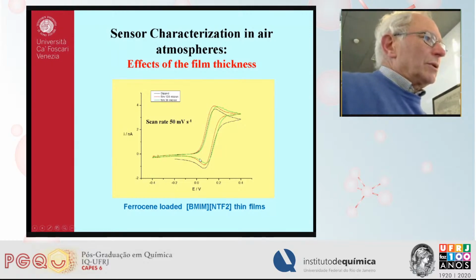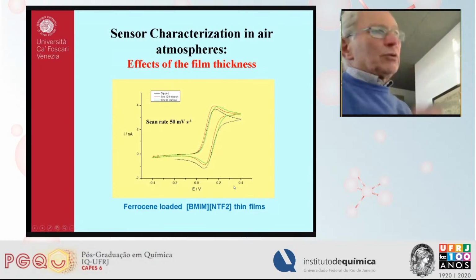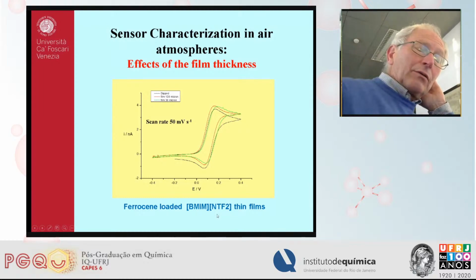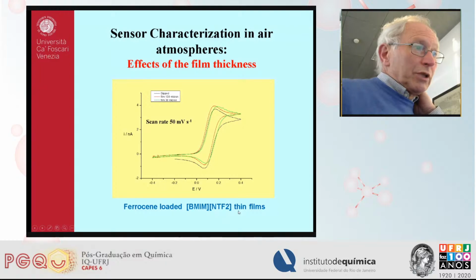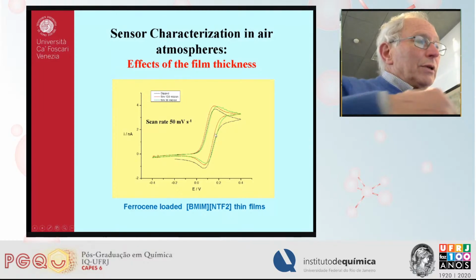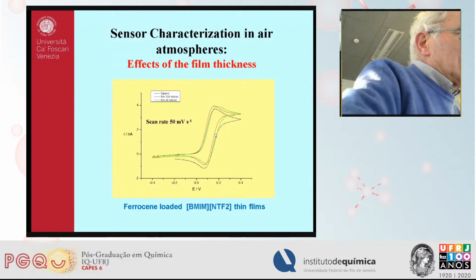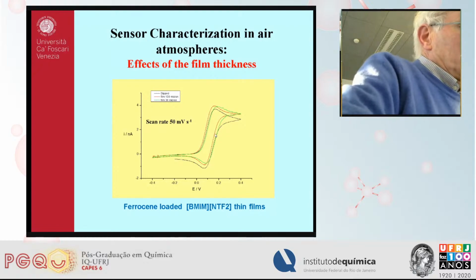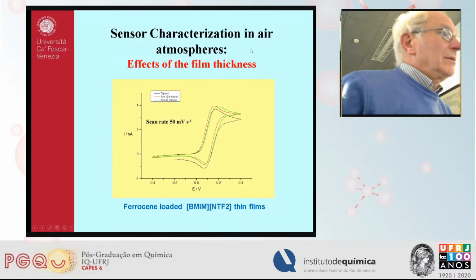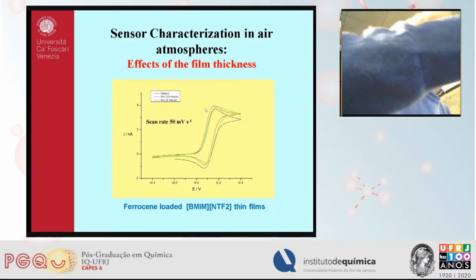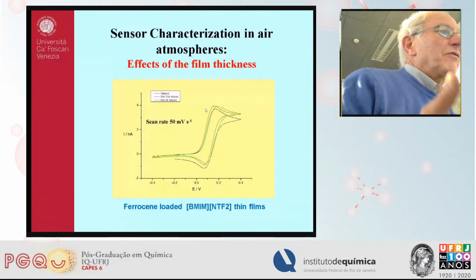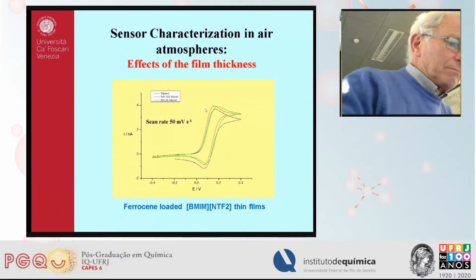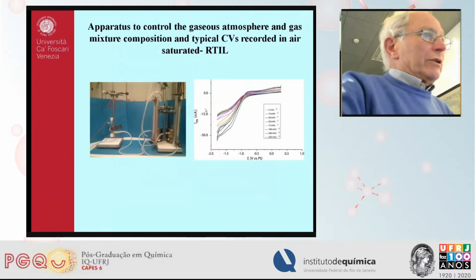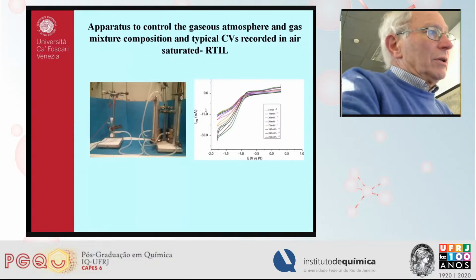These are 2 responses obtained with 2 different thicknesses of the room temperature ionic liquid. So as soon as the diffusion layer within the ionic liquid is much less than the thickness of the ionic liquid film, the responses are almost not affected by the thickness. This means that you can make, with this simple approach, dip coating, a suitable film to obtain suitable responses. Then we moved, of course, to gaseous species, and the first species we explored was oxygen,